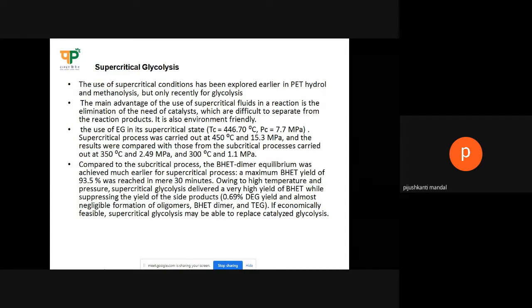So the yield of side products is suppressed: 0.69 diethylene glycol yield, almost negligible formation of the oligomer, BHET dimer, and TEG. If economically feasible, supercritical glycolysis may be used to replace the catalyzed glycolysis process. So here, very important terms are the supercritical glycolysis process, time, and temperature of the glycolysis reaction, where the polymer to monomer conversion is very high within a short period of time. More than 95% polymer to monomer conversion we can achieve by this process.